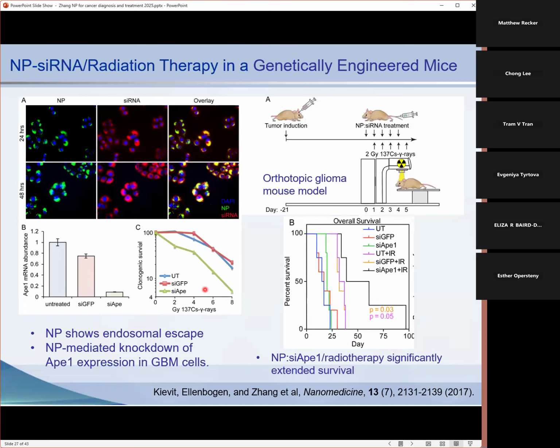interesting, these particles. And then we wanted to see if our nanoparticles can also deliver siRNA against Ape1, which is a gene for radiation resistance. So we wanted to inject this nanoparticle and combine it with radiation in a genetically engineered mouse, which is provided by Professor Erica Holland's group. And we basically found that our nanoparticles similarly can enter the cells efficiently and escape the endosome and can knock down Ape1 effectively, and can also kill the tumor cells when combined with the radiation.